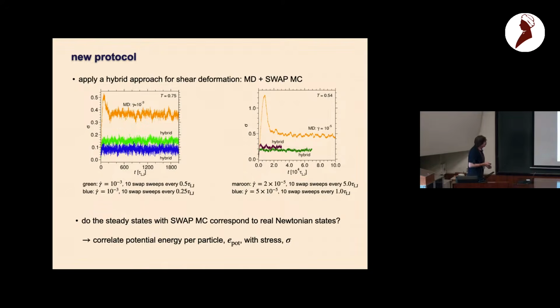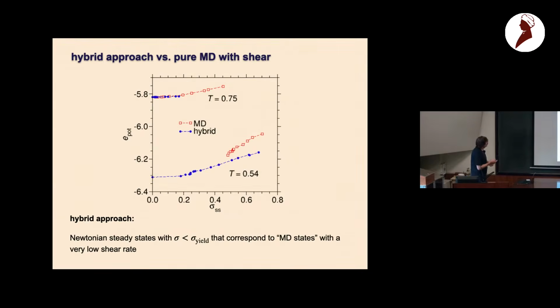And a good quantity to validate this is the potential energy per particle, as a function of the steady state shear stress. This is first of all at high temperatures. These points are from the MD simulations, and this is from the hybrid simulation. We see we have agreement here at low steady state stresses, and this corresponds to low shear rates in this case.